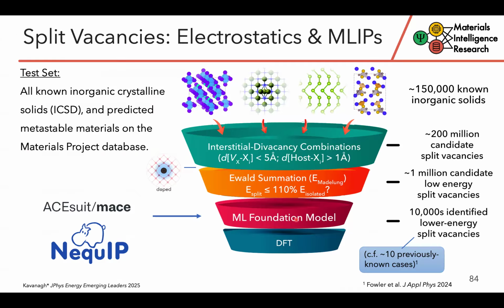And the short summary is that using some of the geometry tools in doped to enumerate all possible split vacancy configurations for cation vacancies in known inorganic solids gives you about 200 million candidate geometries. Using an electrostatic model that reduces to about 1 million candidates, which is then sufficiently tractable to put through one of these machine-learned foundation models, and combined with DFT, it can be used to identify tens of thousands of these types of split vacancy configurations, compared to about 10 previously known cases of such materials.